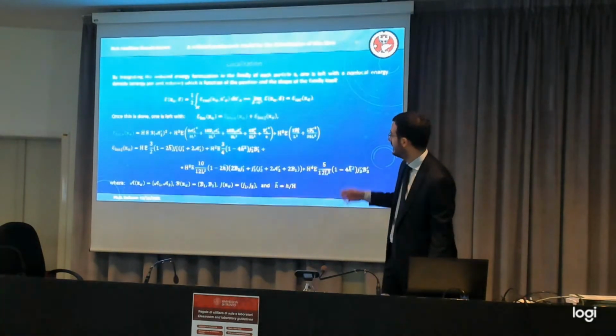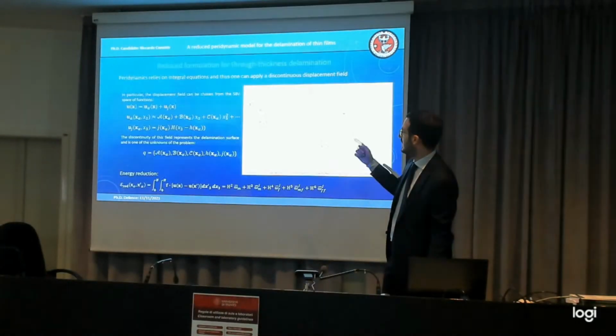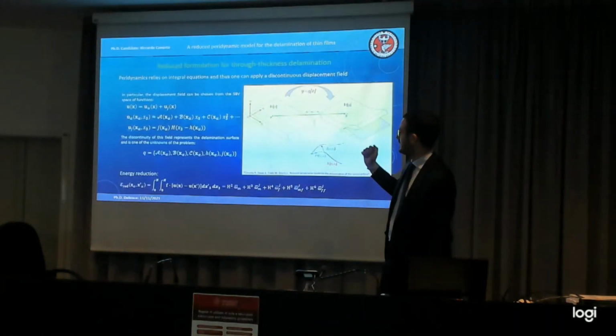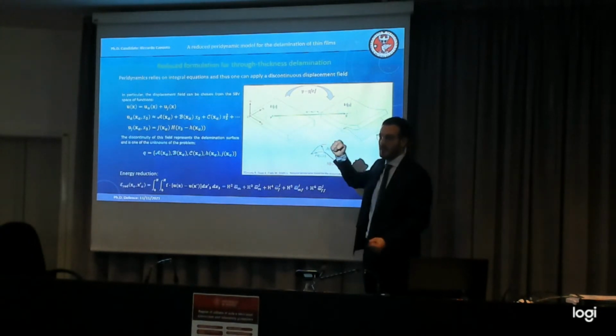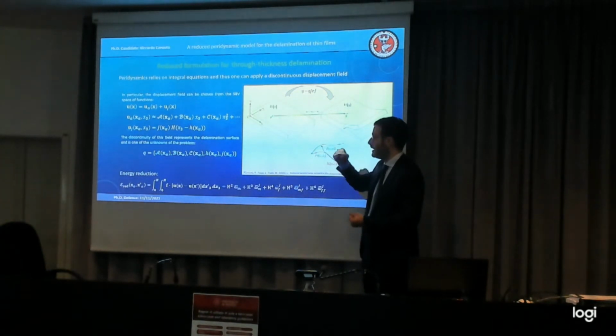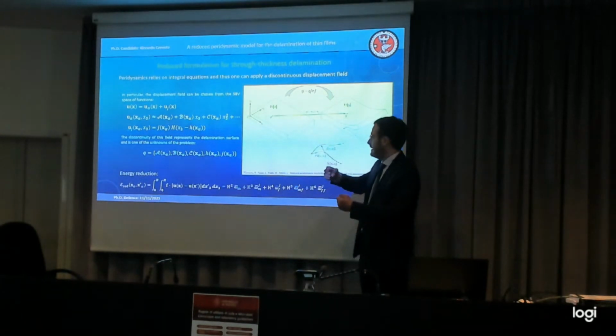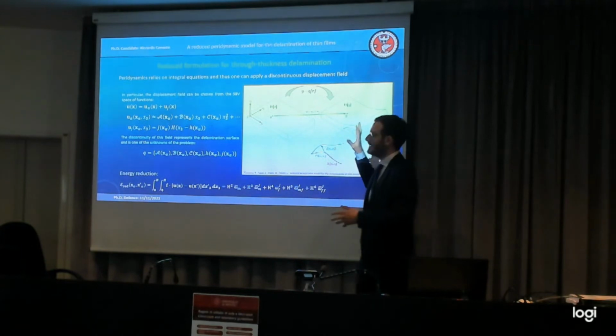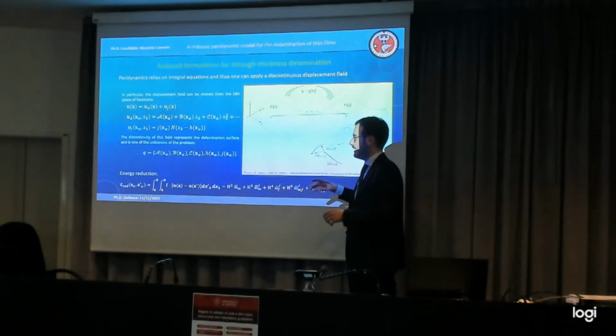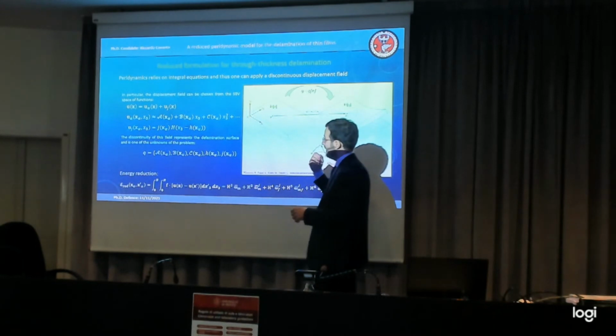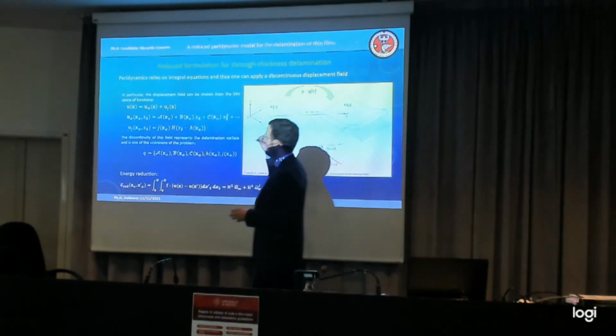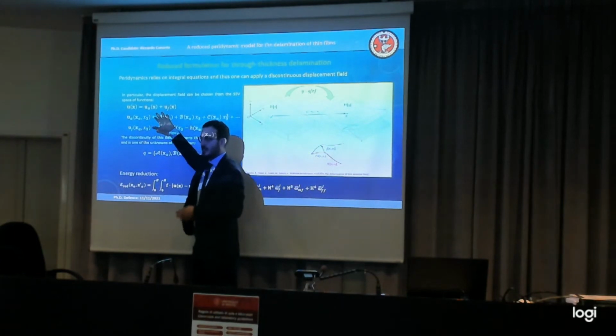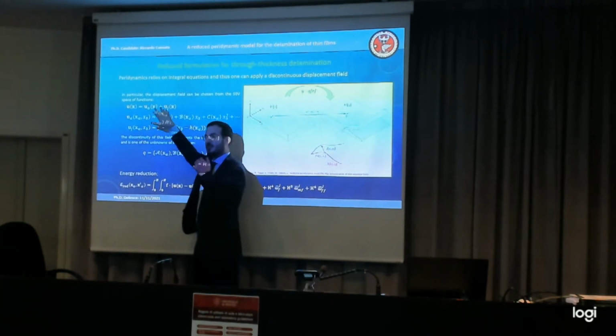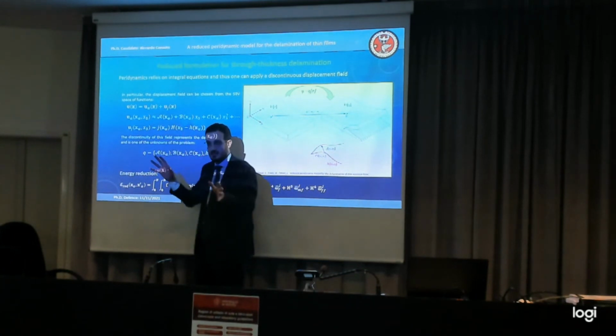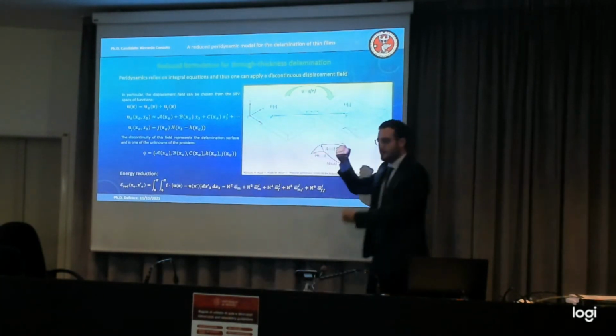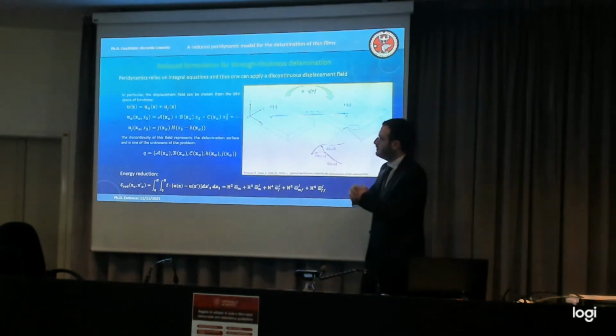And I wanted to say that the non-local model is cohesive by definition, because when the bonds break, the gradual breakage of the material naturally accepts jumps. So the real trick here is that this is not necessarily saying that there is a crack. Jumps are happening, they might not break anything. Unless the bonds break, there is no crack.